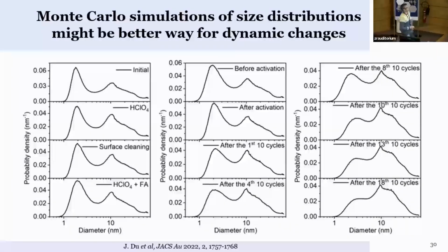What we then went on to do is more Monte Carlo type simulation, where you just don't assume any size distribution. You just add particles, simulate the data, and compare to the measured data. And by this, it's easier to show growing of two populations together. So that's a different system. I don't want to go into detail. So the size difference is larger. You have small particles of platinum and larger particles of gold.